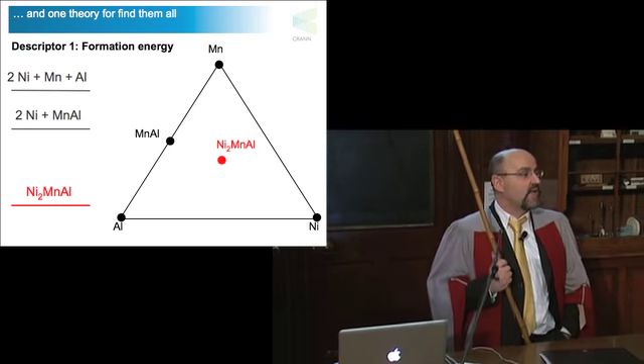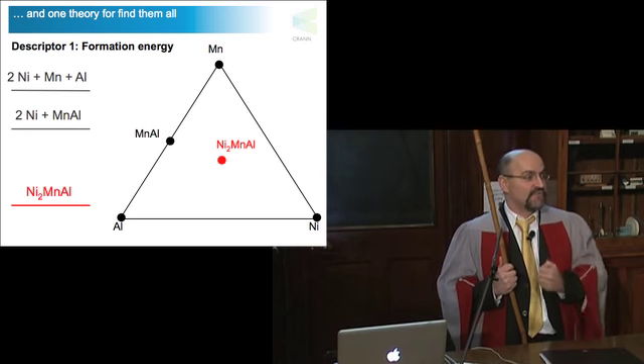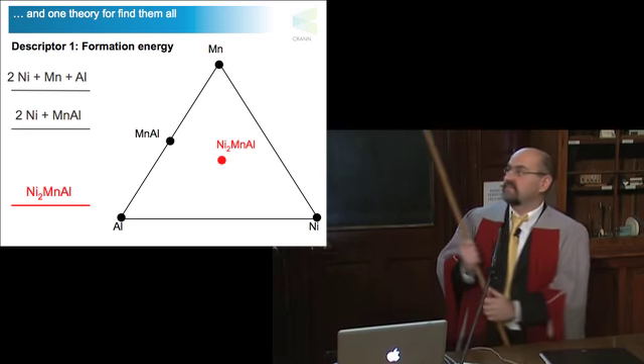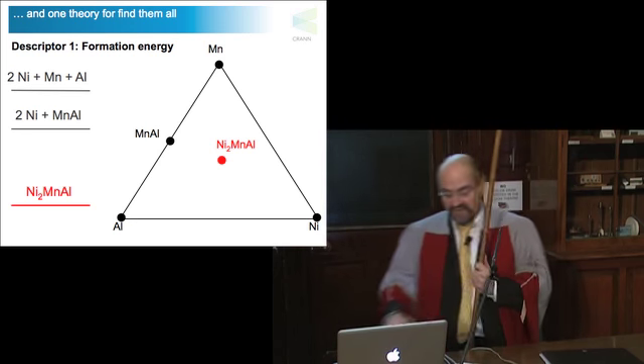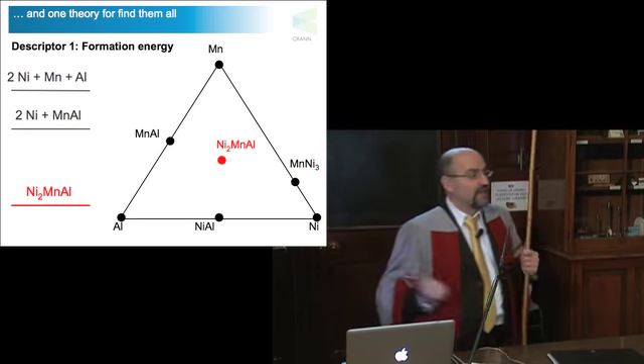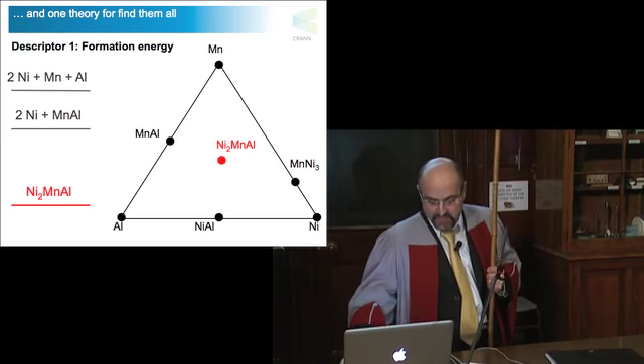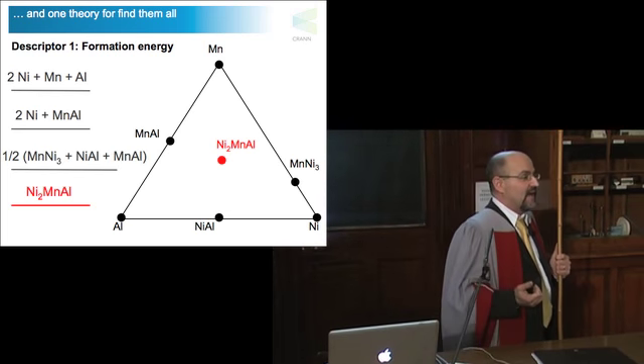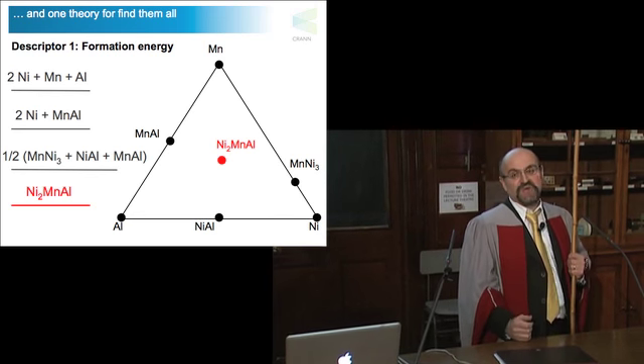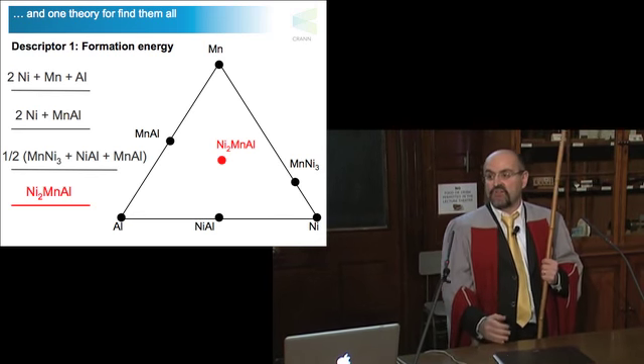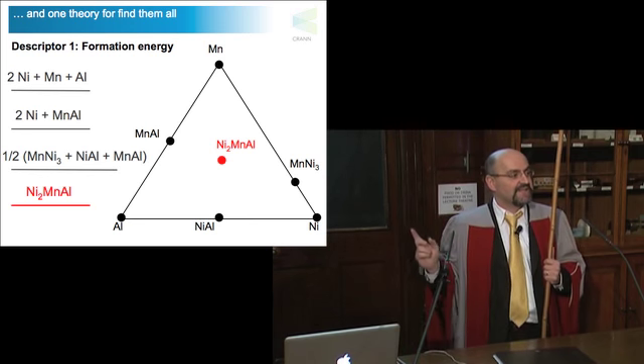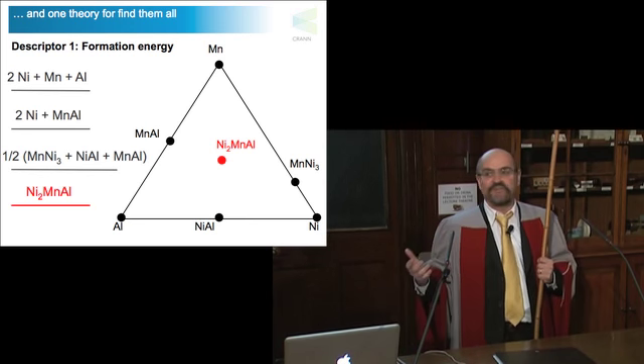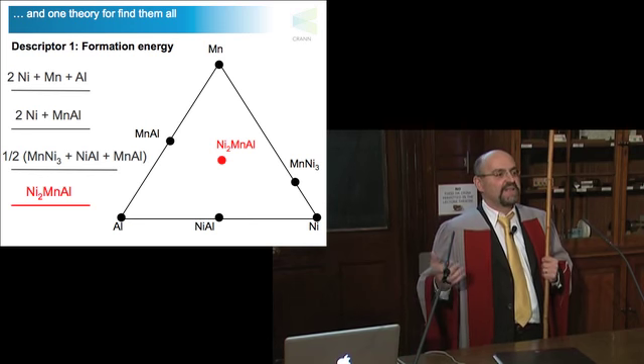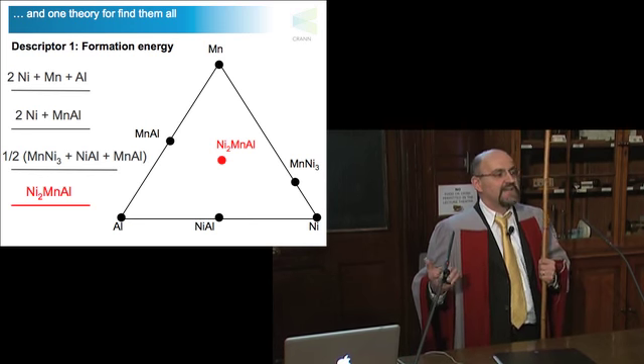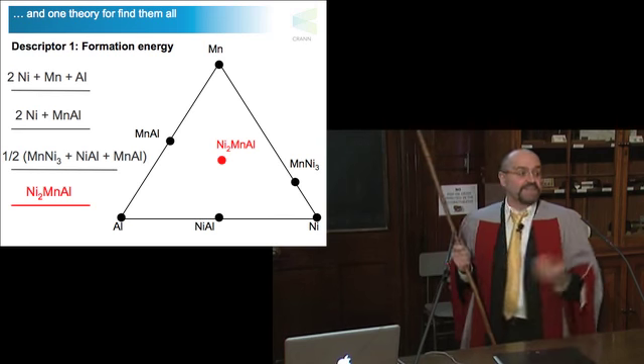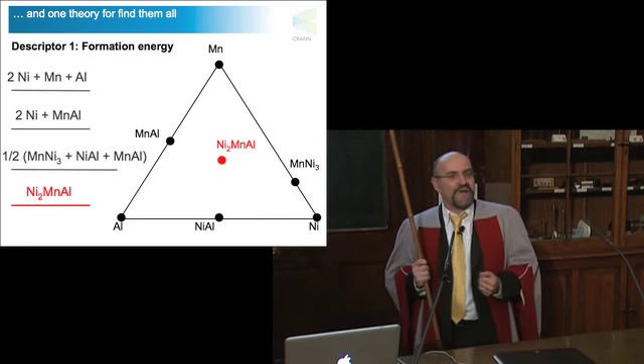And then you have to check that now your material can be made against those two. Now, if it still forms, so the energy is still here, you have to look for more. So you have another two to look at, and you have another composition that can be competitive. And then you have to check all of them. And this, of course, becomes painful, because you don't need just to check the ones that do exist, but also the ones that you have in your database. Because it might be that the material you're looking for that does not exist is competing with another material that does not exist yet. So you have to do all of them.